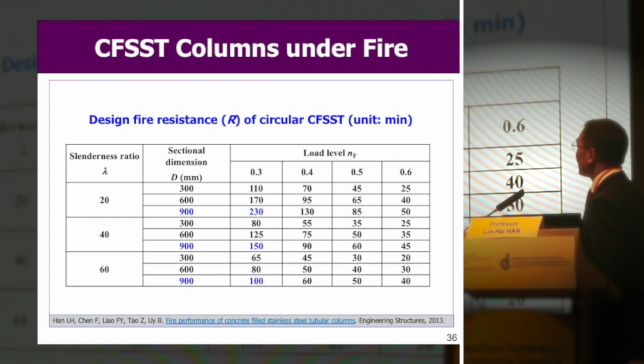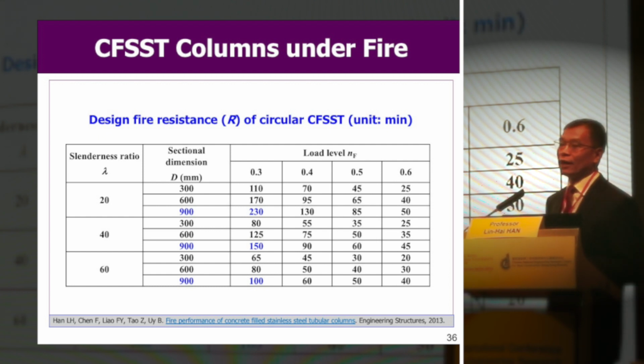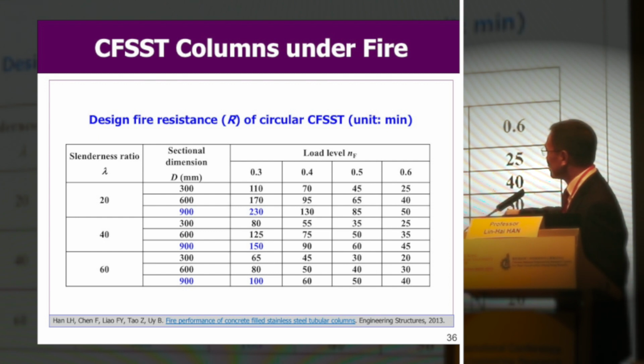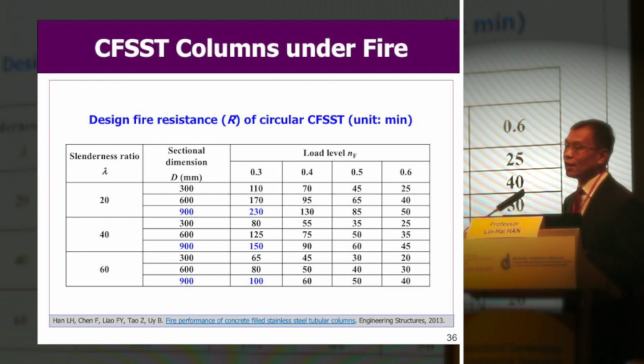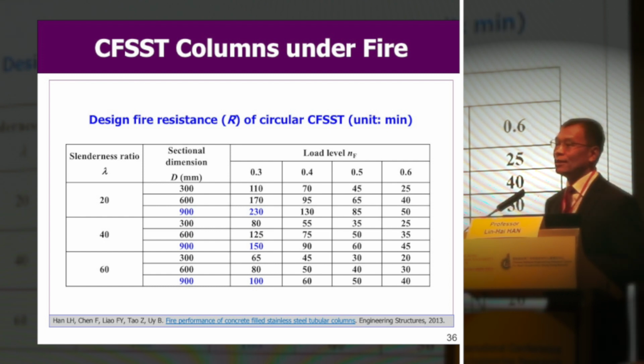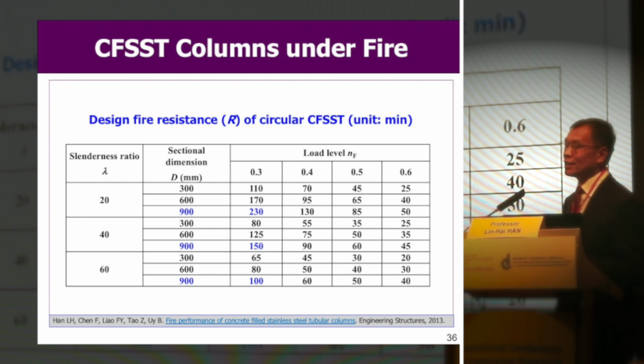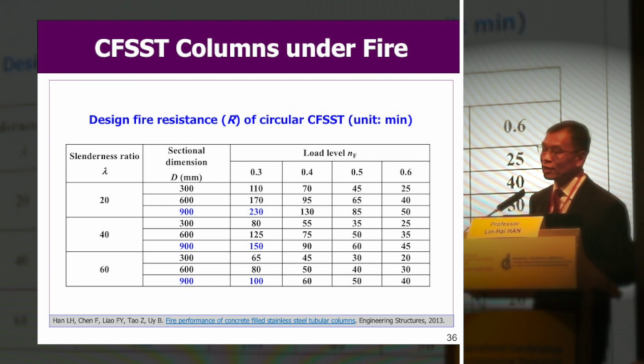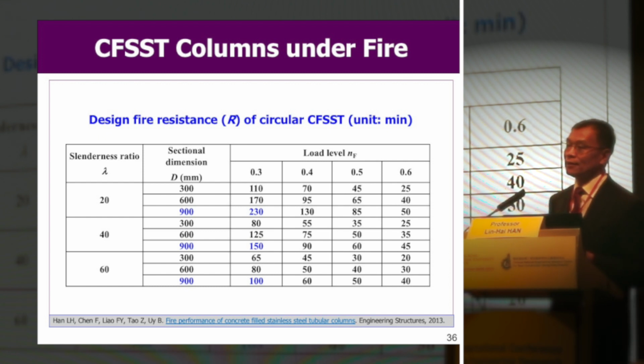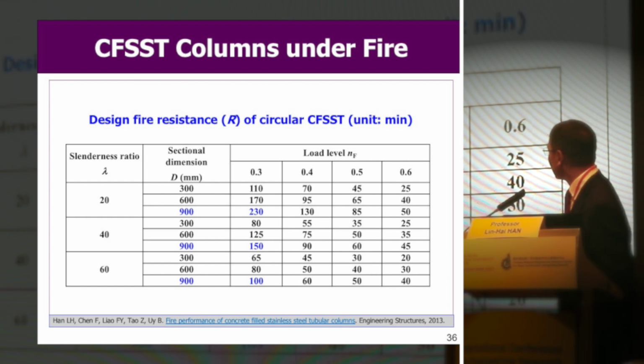Actually, concrete filled stainless steel tube has very desirable fire resistance. For instance, if the slenderness ratio is 20, and the section dimension of circular section is 900 millimeters, without any additional fire protection, the fire resistance could be 230 minutes. So this means that for concrete filled stainless steel tubular columns, we can achieve 3 hours fire resistance without any additional fire protection and even with very high loading ratio during the fire.